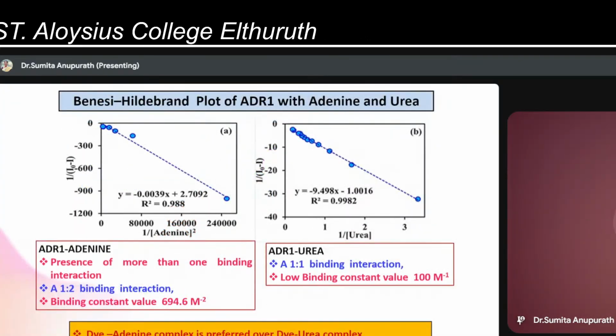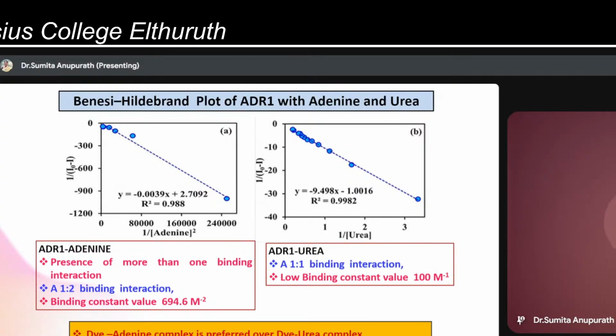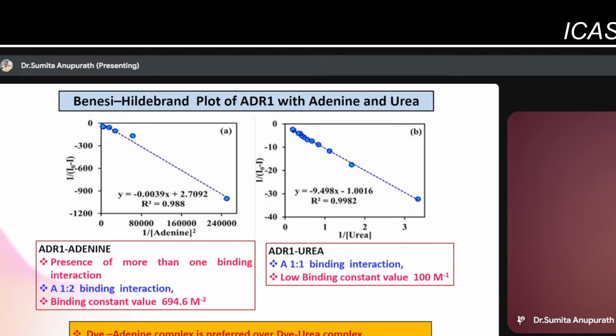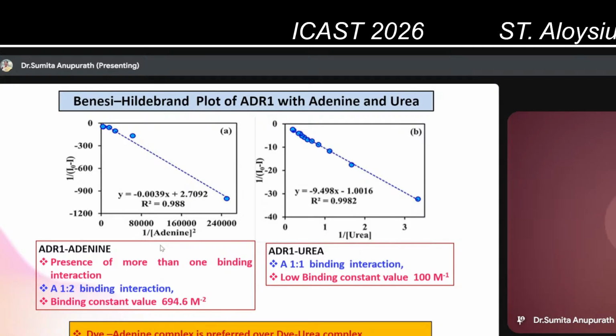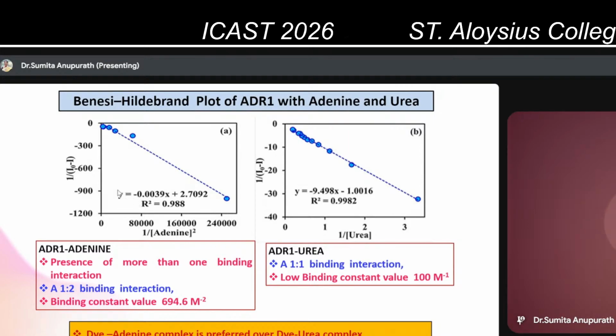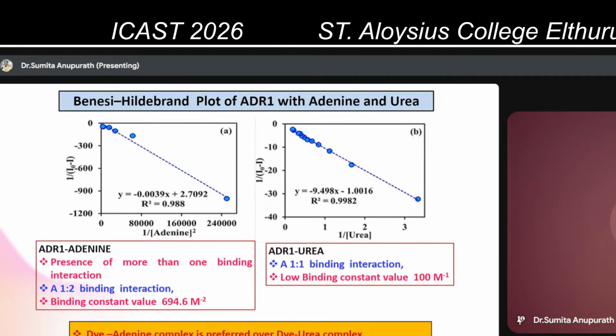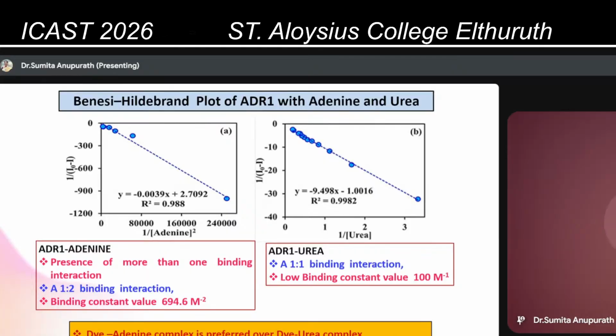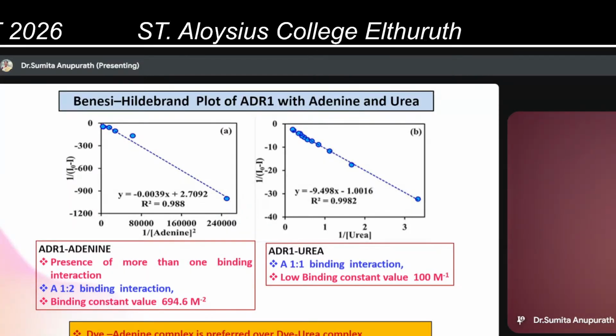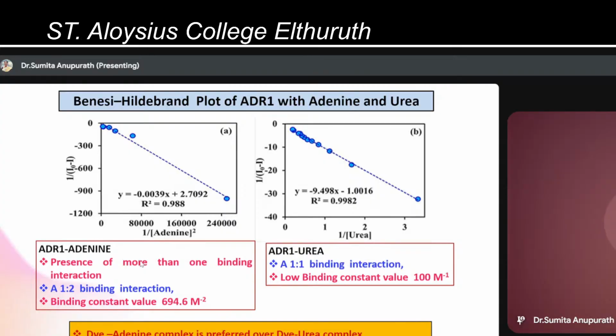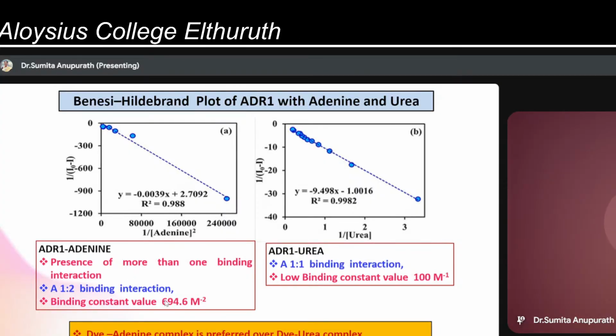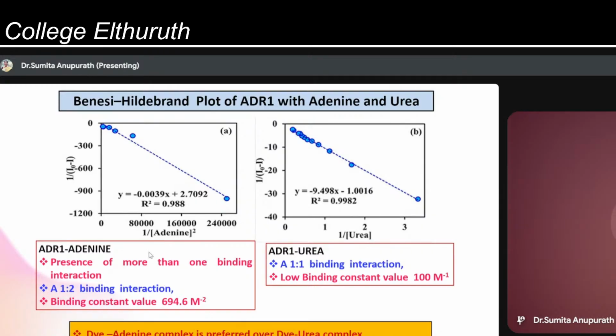To understand the binding nature or stoichiometry, we plotted the Benesi-Hildebrand plot, and we were able to see that the dye and adenine had a 1:2 binding interaction. That is, one dye binds with 2 adenine molecules. So the dye forms a 1:2 complex with adenine, and the binding constant value was also calculated to be high, around 694.6, and at the same time,